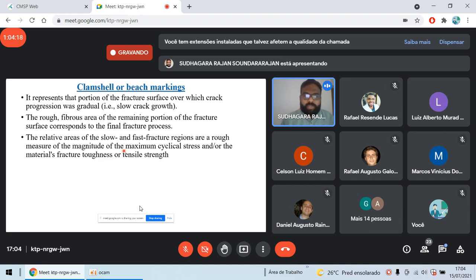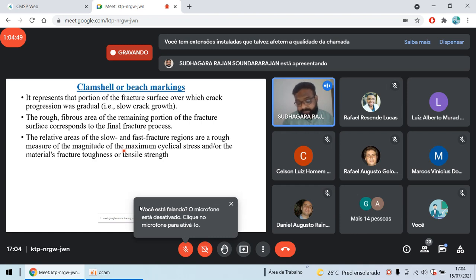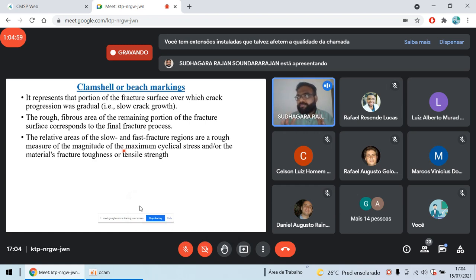So the relative areas of the slow and fast fracture regions are a rough measure of the magnitude of the maximum cyclic stress, the material fracture toughness, tensile strength, everything. So from this relative region, how far the material is resisting the crack, we can get it. If the crack growth region is very small, then the material is said to be a brittle failure. If that is really large, then the material is said to be a ductile failure. So from this information itself, we can make a very rough calculation, or interpret the nature of the material. That's what I'm trying to say.